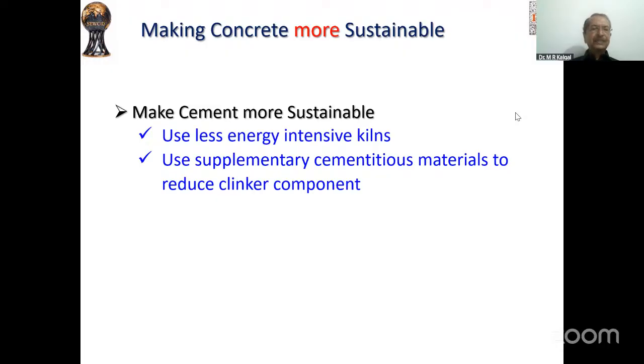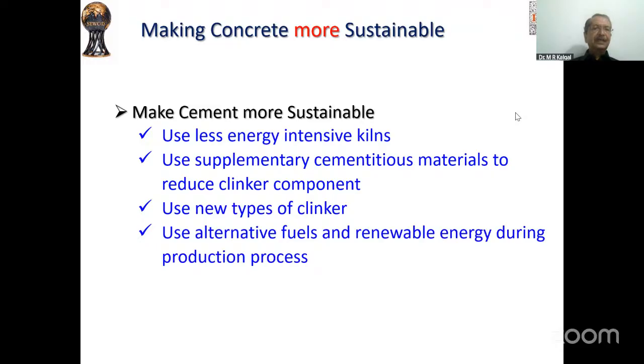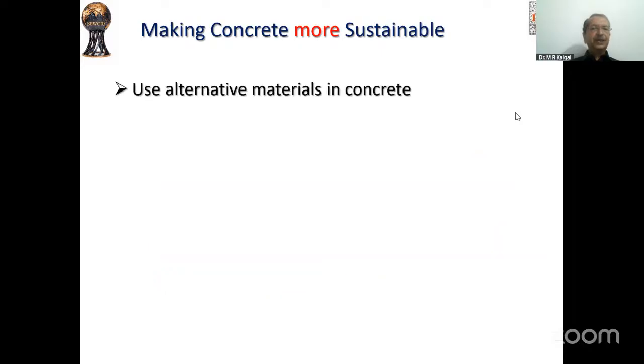So if you take 700 kgs per ton of cement manufactured, and you use 50% GGBS, then the impact is only 350 kgs of carbon dioxide per ton of cement produced. That's an attempt to make cement more sustainable. Then they are trying to use new types of clinker, which produce less carbon dioxide, use alternative fuels and renewable energy during the production process, and if possible, produce clinker-free cement. So from the cement angle, these are the efforts that are going on.